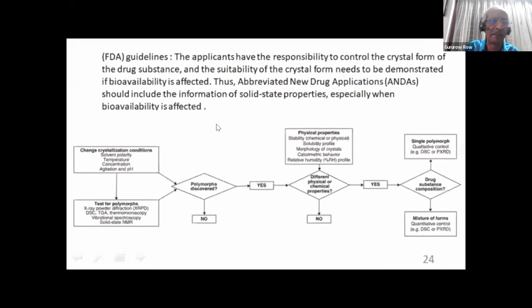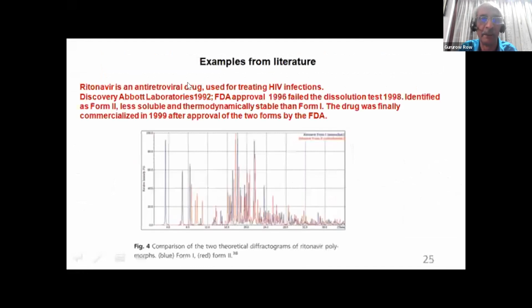This is something which essentially tells us that first, we have to look at different crystallization conditions. Then we look at the test of polymorphism. Then once we say the polymorphism is discovered or not, if it is not, we ignore it. If it is discovered, we say yes, and then measure all the physical properties, measure the stability of the compound, and then see if there are different physical or chemical properties. Then the composition of the drug substance is analyzed to see whether it gives a single polymorph, which is a qualitative control using DSC and PXRD. And using DSC and PXRD, again, we describe it as a mixture of forms, and that will give us a quantitative control. That means we can have 2 different forms in different ratios, and still it could be an effectively new drug. So the discovery of the drug, therefore, goes through these procedures, and then only it is accepted.